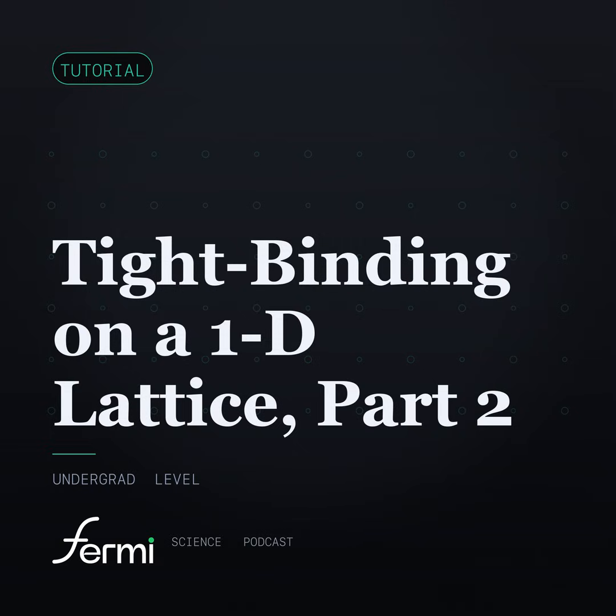Precisely. It's a full band with a gap, but a modest one. Silicon has its lower bands exactly filled, with a gap above of a bit more than an electron volt. At absolute zero, that makes it a perfect insulator, nothing in the empty band. But that gap is small enough that ordinary warmth, room temperature thermal energy, kicks a handful of electrons up across it into the empty band above. Now you've got a few electrons rattling around up top and a few holes left behind down below. A trickle of conduction, and one you can dial.